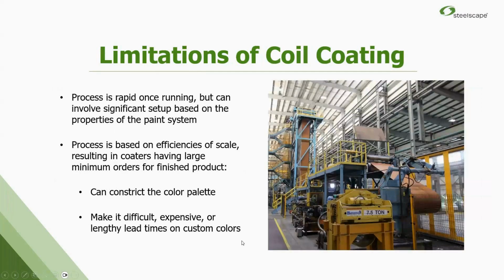The limitations of this, though, are that once we're running, we need to run for long periods of time. So we don't like to do small jobs. We don't like to change the paint very often if we can avoid it. So this can restrict the color palette a little bit, and it restricts the order size. We can't run just a few hundred feet of product. A lot of these paint lines hold anywhere from 1,000 to 3,000 linear feet of product from end to end. So the quantities are quite large.